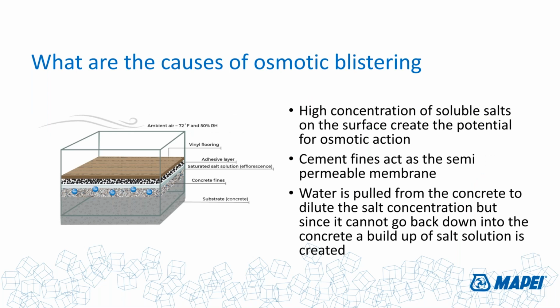But when I put an impervious moisture vapor barrier on top of it in the form of a vinyl sheet flooring or an LVT or something like that, I blocked the evaporation process. The liquid that was being pulled from the concrete slab, mixing with that salt concentration that was happily evaporating and not creating any problems, now can't evaporate, but the process still goes on. So that high concentration of salt compound on the top layer of the surface of the concrete slab is sucking moisture out of the concrete below it in an attempt to equilibrate itself.